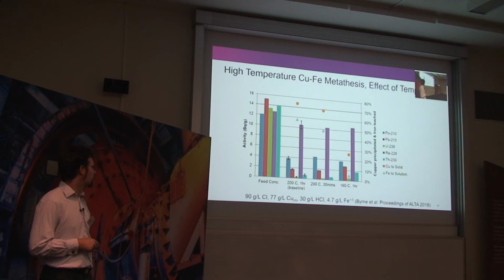And the second result from this study is the effect of the operating conditions. So 1 hour residence time is long, that means quite a big autoclave. So if the residence time can be shorter, you get a smaller autoclave. If the temperature can be lower, then that's a lot of energy savings. So this is just a couple of tests where we looked at the baseline conditions, 200 degrees, 1 hour, 200 degrees, 30 minutes, 160 degrees, 1 hour.